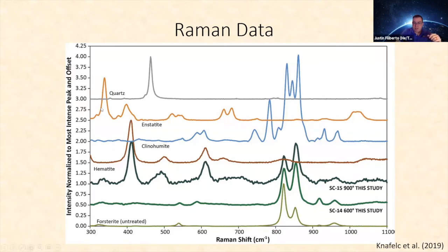Interestingly, there's a peak here consistent with enstatite. You can see potential evidence of the doublet here. And so there may be other minerals forming as we go to longer and longer times of experimentation. But the main minerals that are forming are olivine going to iron oxides in this.